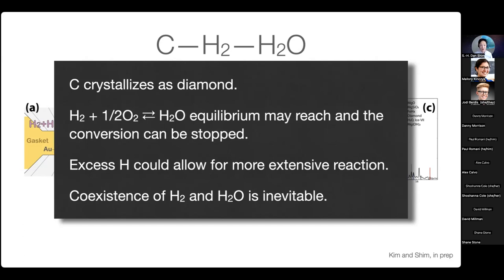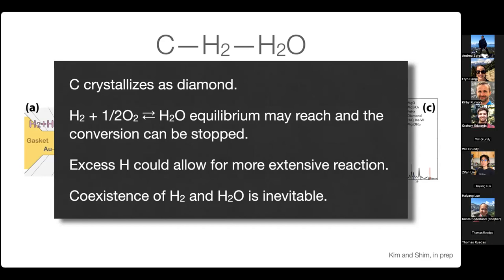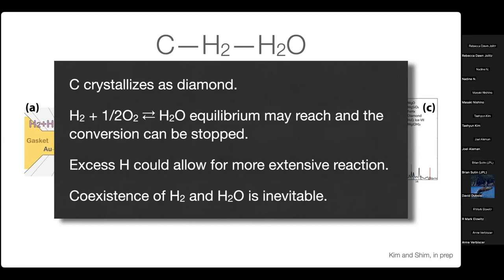And we find that by using different prescribed ratios between hydrogen and water, the carbon reduction stops happening at a particular hydrogen-water ratio, which means that the chemical balance, or chemical equilibrium, between hydrogen and water will be very important to a model where this conversion will stop and the planet structure more or less remains constant afterwards. Yet what I also want to emphasize is that if you have excess hydrogen, much more hydrogen than the rock, then you will dilute the water in the system, allowing a more extensive conversion from the hydrogen-rich version to the water-rich version for those types of planets.